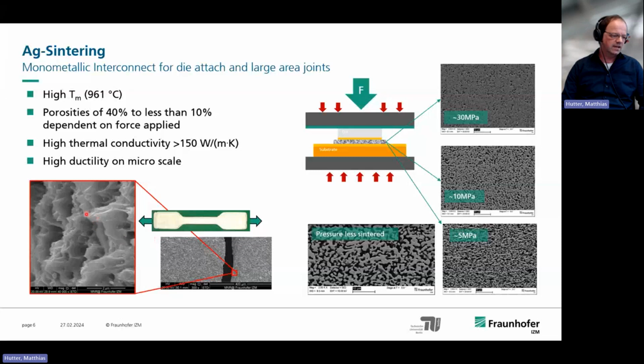If you look at the microscale, you see that, of course, because silver is a plastically deformable material, you see these plastic deformations. So it can accommodate stresses, but the creep resistance is much higher than that of solder, and therefore it is very promising for higher lifetimes.